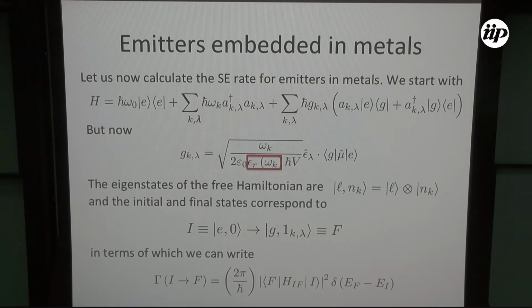And recalling that the calculation is 2 pi over h bar, something squared, density of states, I want to use Fermi's golden rule. And in order to do that, I have to define my initial and final states. So for the non-interacting Hamiltonian, I can split these two states into excited state and 0 photons. This is my initial state. Ground state, 1 photon. This is my final state. And I can calculate the transition amplitude.